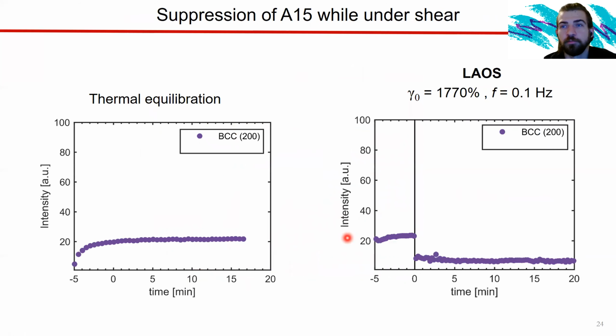What surprised us, though, is that by lowering the frequency at that largest strain amplitude, we actually saw a suppression of A15 entirely throughout the duration of the experiment, where we only had BCC. And the reason this intensity dropped is because the peaks broadened a lot. So the intensity drops and the peaks broaden, which tells me that the grains are getting very small during this shear. The crystalline grains are getting very small.